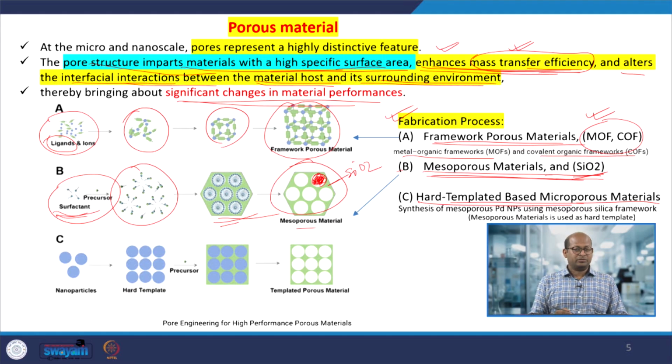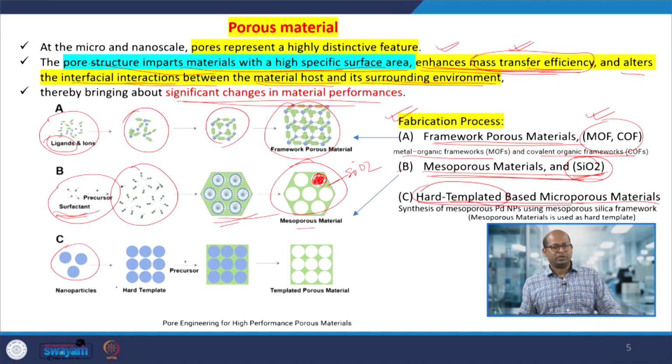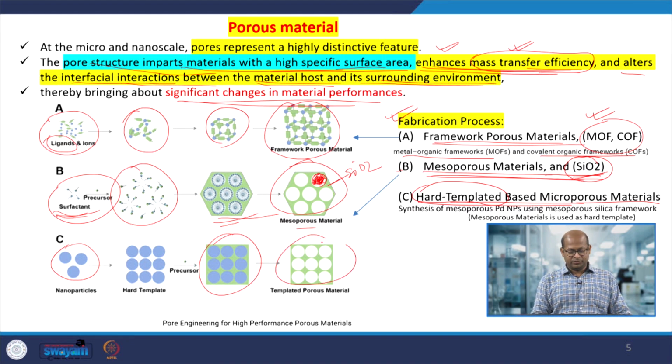and we can measure the pore dimensions, and based on that we can say whether it is mesoporous or another type of pore has developed. Once we are able to develop this type of highly porous material, it can also be used as a hard template for the next preparations. We can use any precursors, which would be distributed in this mesoporous solid or silica, and then this type of framework forms, and after that we can eliminate or dissolve the SiO2.